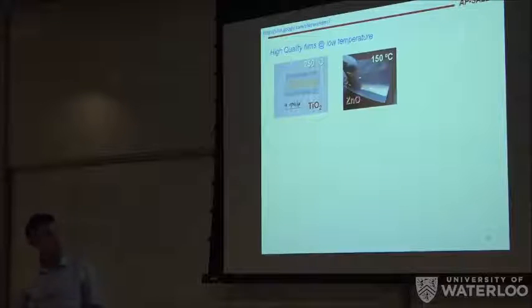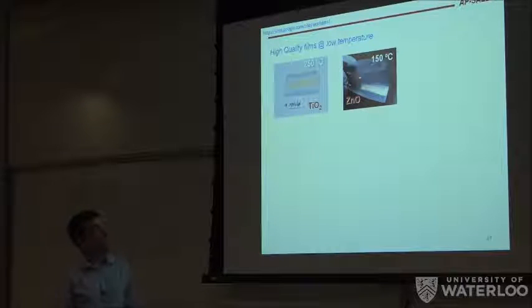These are some of the samples we used to deposit at that time in Cambridge, where we started developing this equipment from Kodak. This is TiO2 deposited at 250, already crystalline, very homogeneous, over centimeter scale. This is 6 centimeters by 6 centimeters. Again, because we can do it at low temperature, we can use plastics as substrates.